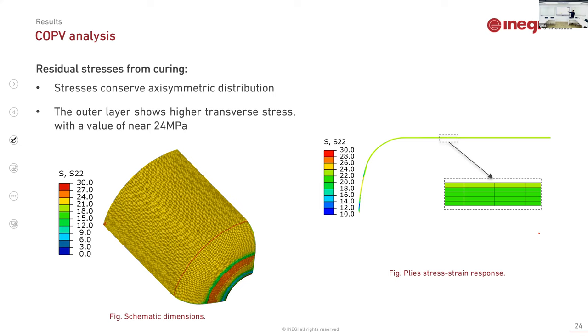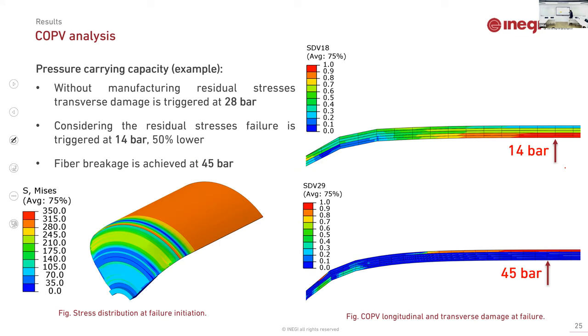Now we apply the same methodology, but using the macro pressure vessel model, and we repeat the curing simulation. We see that the residual stresses in each one of the laminas have more or less the same order of magnitude that we get in the sublaminate model. In this case, the outer lamina is what gets the higher transverse stress. If after that we apply pressure, what can we see?